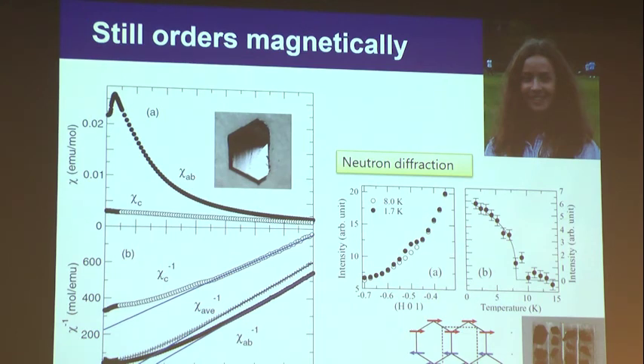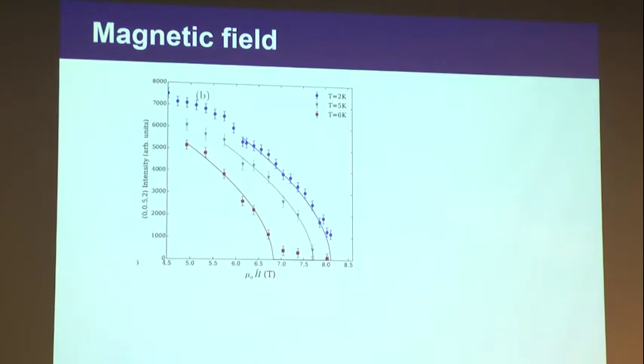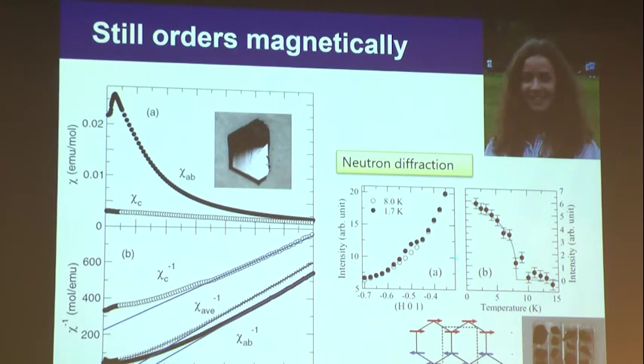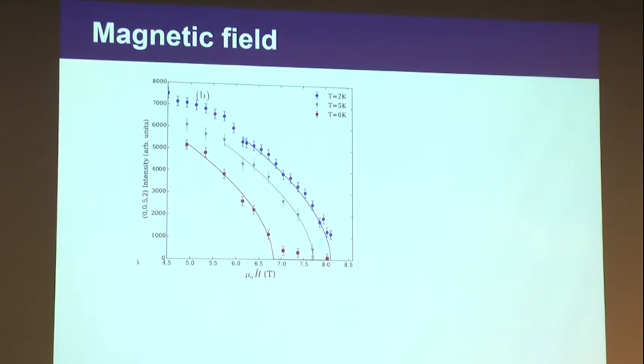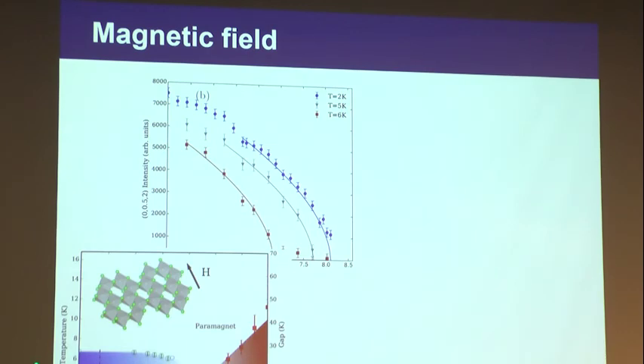That's the same as sodium iridium oxide. But the interesting thing about this one is that it's not the end of the story, because when you apply a magnetic field, something interesting happens. This magnetic ordering peak that I showed you looks very small, but it actually decreases and then goes away when you apply a magnetic field of about 8 Tesla. That's an incredibly small magnetic field scale, actually. You can plot the phase diagram of temperature and magnetic field, and you can see that the magnetic order is suppressed at 8 Tesla.